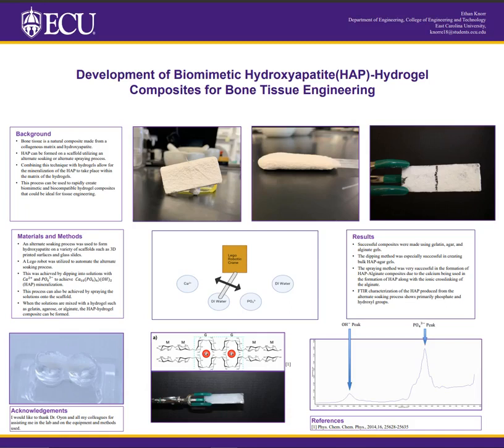The solutions used in the alternate soaking process can also be put into spray bottles and be nebulized onto the scaffold. This method was effective and allowed for more bulk samples to be produced quicker. The dispersion of the solutions on the scaffold from spraying allowed for a more even coat all around.